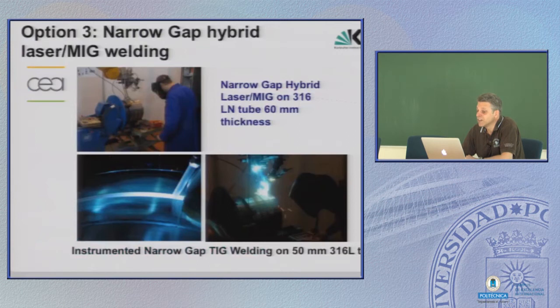So let's come to the next option, also a very specific, probably unique weld technology at CEA. They developed a mix of laser welding and using a filler wire. In principle, it's TIG welding without TIG. Well, it sounds strange. You use the weld material, the weld wire, but melted by laser. That's the principle. Again, this comes from fission technology. Also here it worked quite well with austenitic steels.